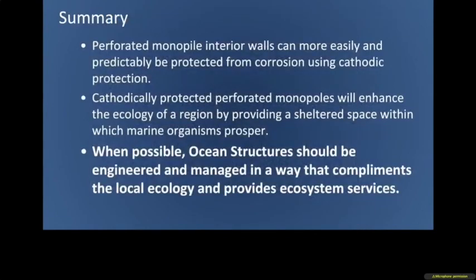So what did we learn? Perforated monopile interior walls can be more easily and predictably protected from corrosion using cathodic protection. Cathodically protected perforated monopiles will enhance the ecology of a region by providing a sheltered space within which marine organisms prosper. And I think the lesson which is probably most important from my point of view is that when possible, ocean structures should be engineered and managed in a way that complements the local ecology and also hopefully provides some ecosystem services.